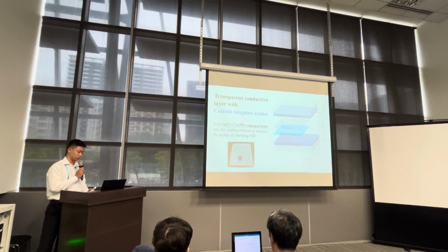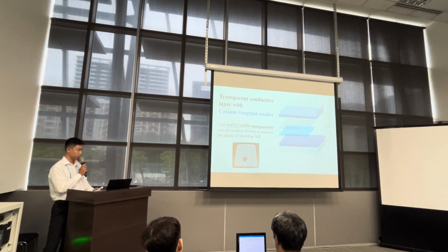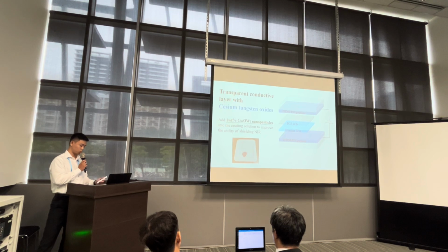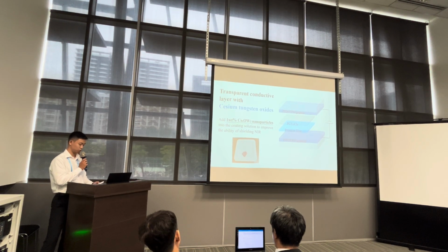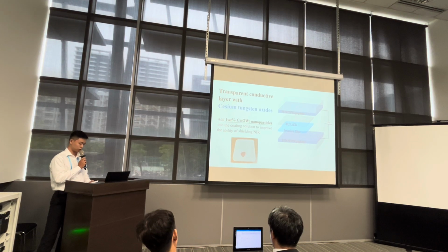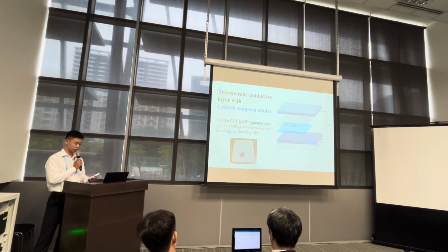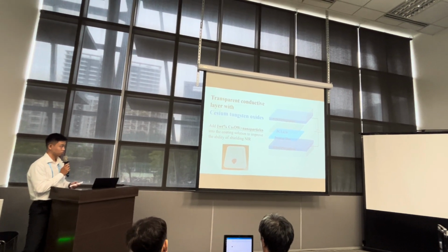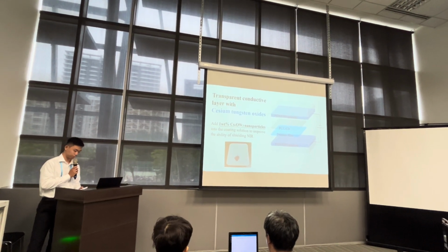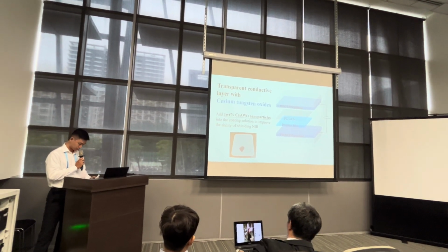And as mentioned in the topic, in order to improve the device's ability of shielding near-infrared, we add a little bit, 1 weight % of cesium tungsten trioxide nanoparticles, just like the powder, directly into our coating solution, the precursor. Using the same method and same scale, we fabricate another set of transparent conductive oxide and another set of device.